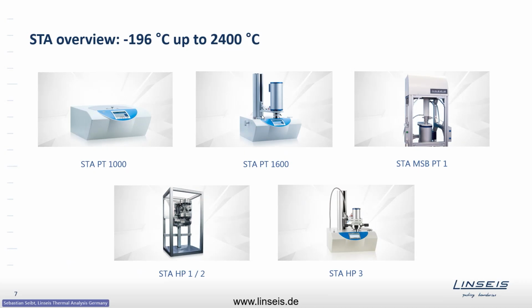And this platform can do more or less any condition we offer. On the left side, there is the lower edge. That's the STA PT1000, and as the name suggests, it goes up to 1000 centigrade. However, here you do not have a flexible, modular, exchangeable furnace. Here you have an integrated furnace. It's always the same furnace that goes up to 1000 centigrade. So it's for a very specific experiment, and it's for the lower temperature range. It's a little bit faster due to the lower thermal mass. However, the possibilities and options are restricted.